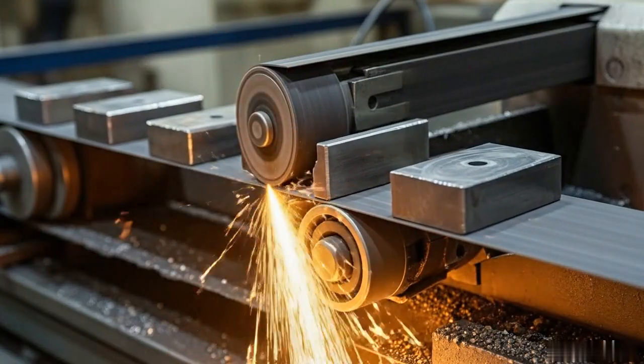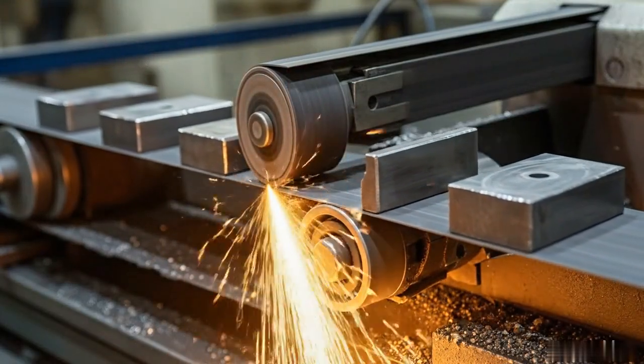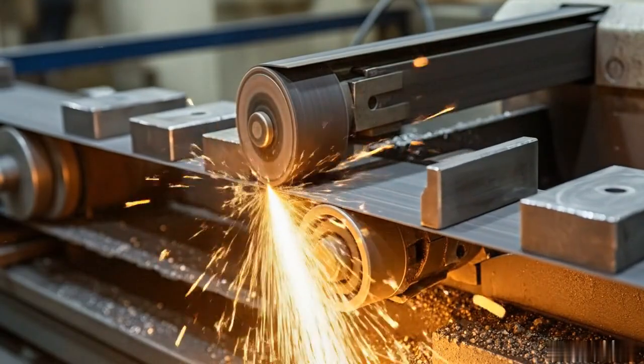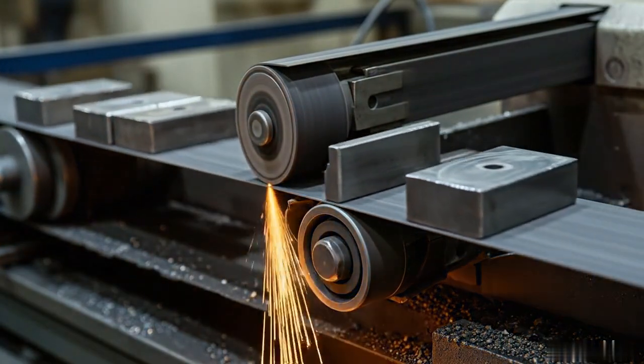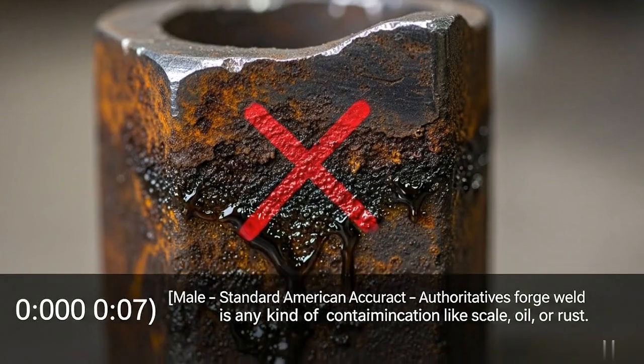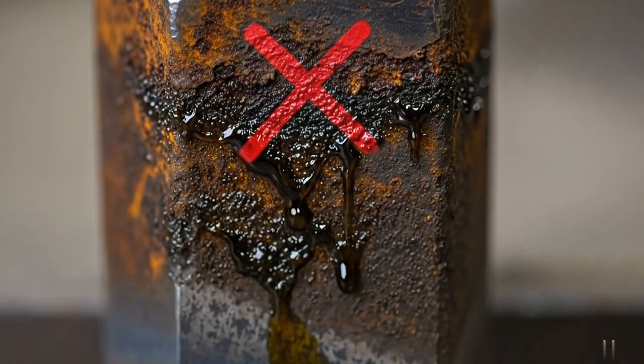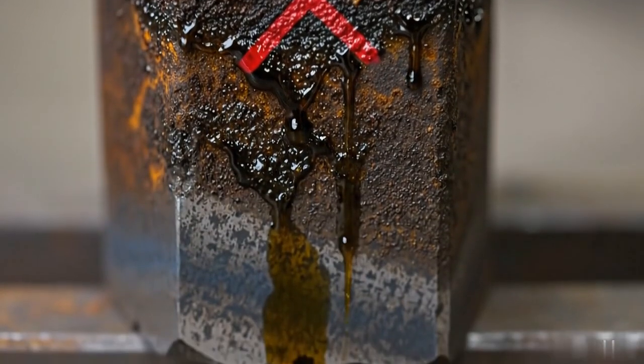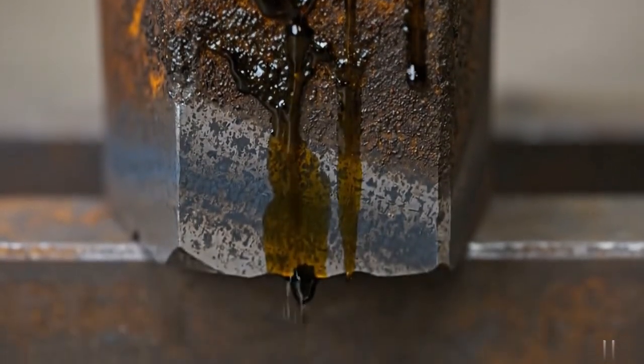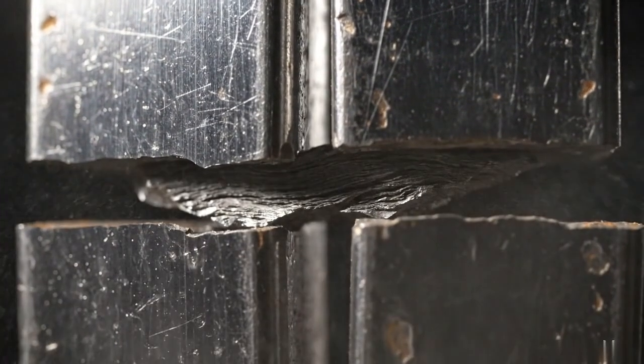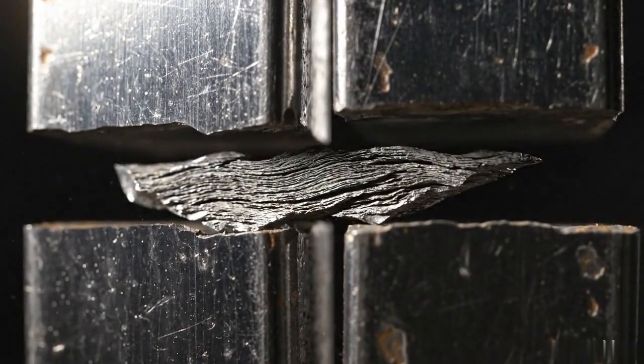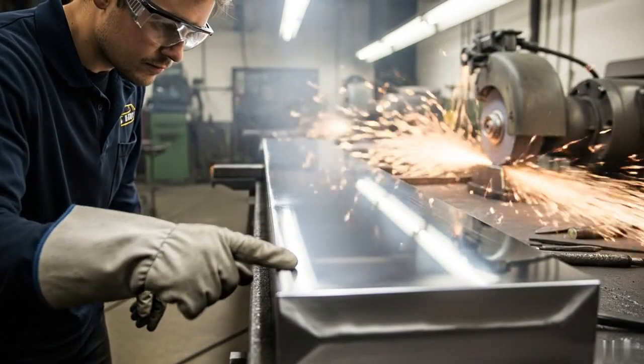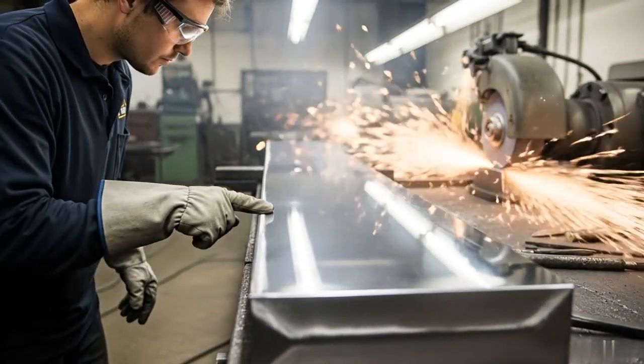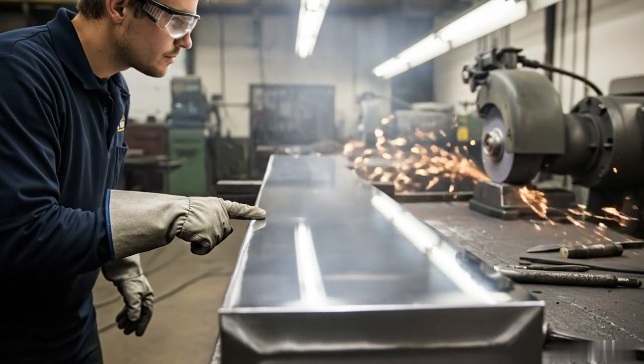Now, before these layers can become one, they have to be perfectly clean and free of dirt. The enemy of a good forge weld is any kind of contamination, like scale, oil, or rust. Anything that can create a tiny gap is a weak spot that can cause the blade to delaminate. We grind the surface of each bar until it shines a raw, clean silver, ready for welding.